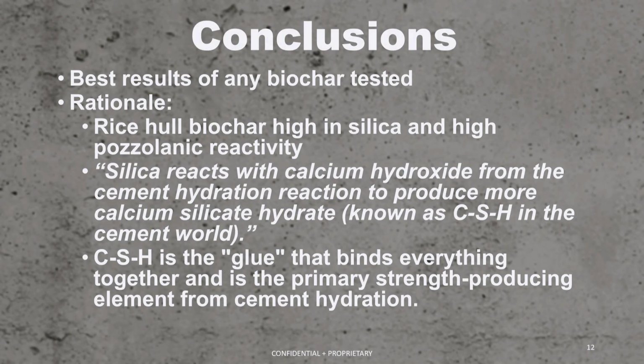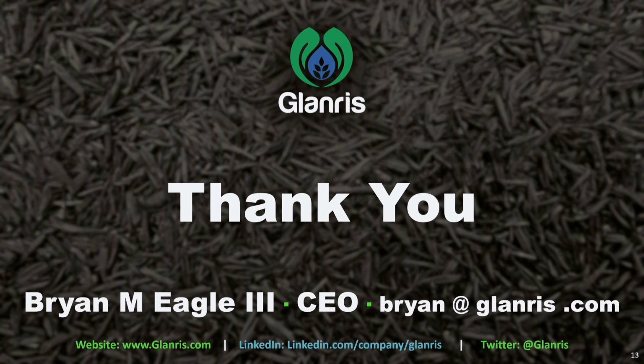So, reading from the reports that are about to come out on these two peer-reviewed studies, what they found is that rice hull biochar had the best results of any of the biochar tested. And just to get into the why, basically it's the silica reacts with the calcium hydroxide to form what they call CSH in cement terms, which is really the glue that binds everything together. And it had the highest scores of any of the materials that they tested. So very excited about these reports coming out and about this potential application. Happy to answer any questions.